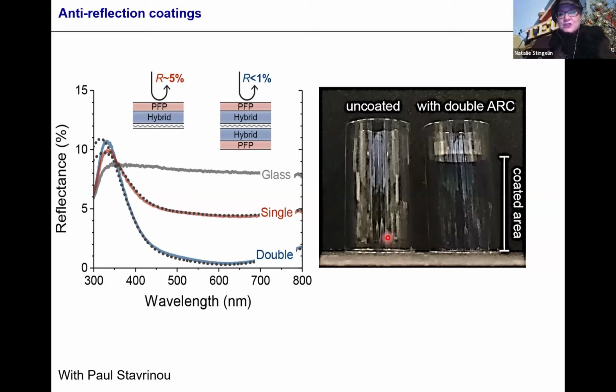This is the tube I showed you before, and after coating. And once you coated it, you see the reflectance is drastically reduced. So actually the glass nearly looks black.